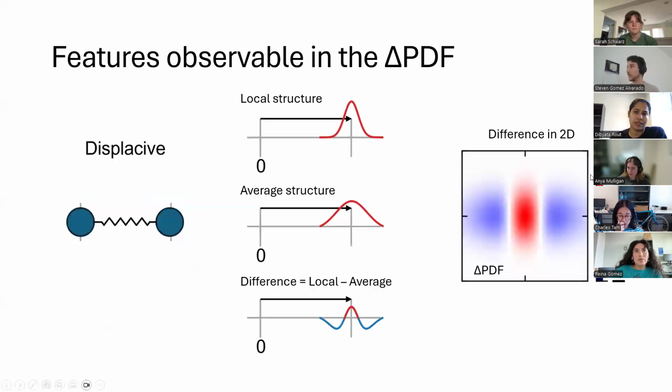And then the last one. Uh, yeah, go ahead. Can I ask something? Yeah. So usually when we do X-ray diffraction, we take care of the instrumental broadening. Mhm. Here it's already taken care of? Define taken care of, I guess. Because these peaks I'm talking about are in real space. These are the electron densities as a function of distance, right? Yeah. So, ideally the instrumental broadening in your diffraction experiment should be much, much narrower than the peak width of the diffuse scattering, right? Because diffuse scattering inherently is super broad. Okay. Yeah.